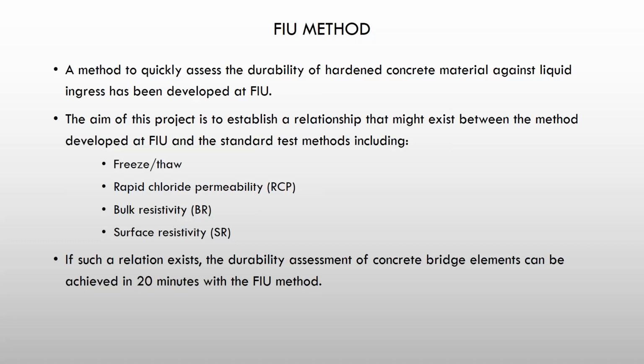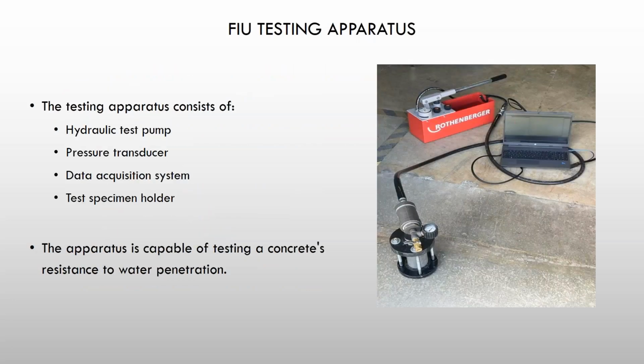The aim of this project is to establish a relationship that might exist between the method developed at FIU and the standard test methods, including freeze-thaw, RCP, bulk resistivity, and surface resistivity. If such a relationship exists, a durability assessment of concrete bridge elements can be achieved in 20 minutes with the FIU method. The FIU testing apparatus consists of a hydraulic test pump, pressure transducer, data acquisition system, and a test specimen holder. The apparatus is capable of testing concrete's resistance to water penetration.